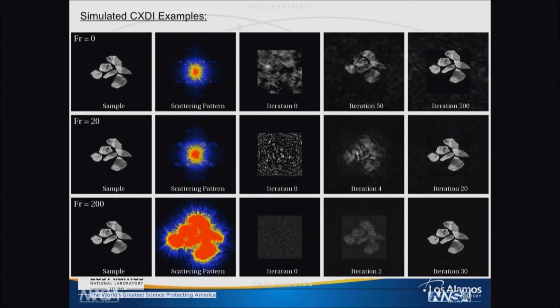So here are some examples at Fresnel numbers very much greater than 1. If the Fresnel number is 0, classic iterative phase retrieval in the Fraunhofer regime, here's a scattering pattern, and after 500 iterations, you basically predict what the image looks like. But at 20, the scattering pattern again looks kind of similar but different, and as you go through the iterations, it actually converges faster. We do not have a mathematical proof about why it converges faster at larger Fresnel number, but the iterations seem more robust. At 200, which is really getting to be in the near field, it sort of starts looking like a phase contrast image in some sense.